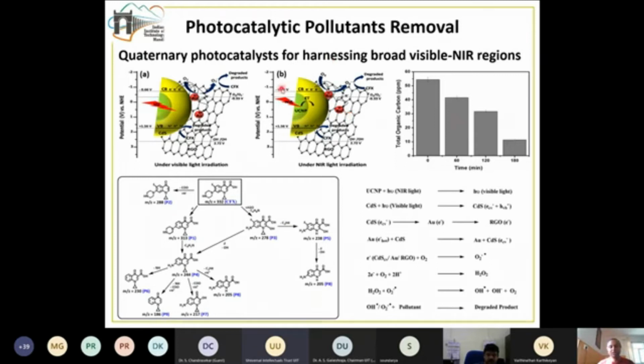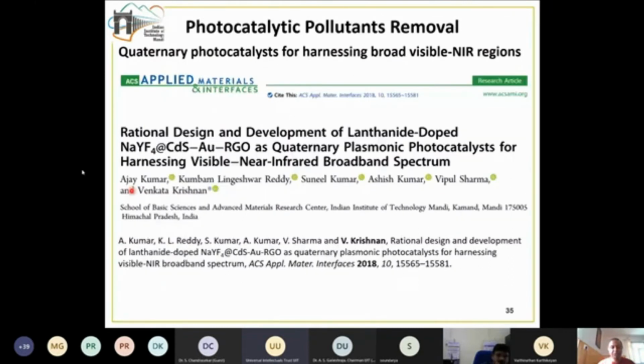So we also did the total organic carbon content measurement, TOC measurement, and found that as a function of time, the total organic carbon content is decreasing, which means that the carbon is getting converted into much smaller fragments. And similar to the previous work, we also did a detailed degradation pathway analysis, wherein we saw how this ciprofloxacin gets degraded into much smaller fragments. Based on this, we also came up with certain equations to explain the process. This work was also done by one of my former PhD scholars, Dr. Ajay Kumar, and this was published in ACS Applied Materials and Interfaces in the year 2018.